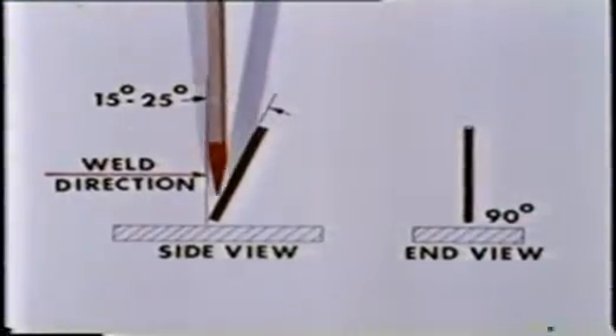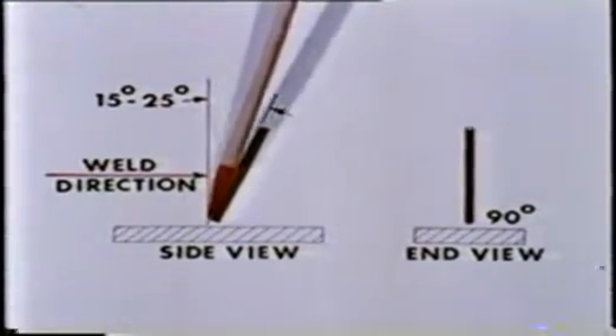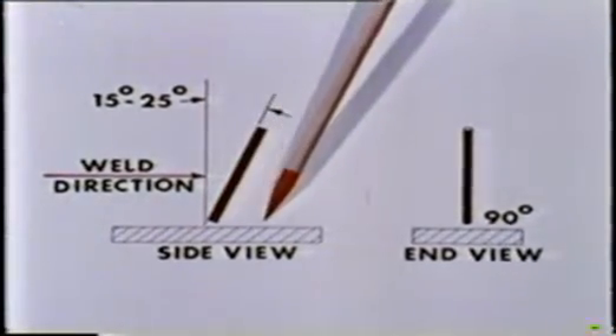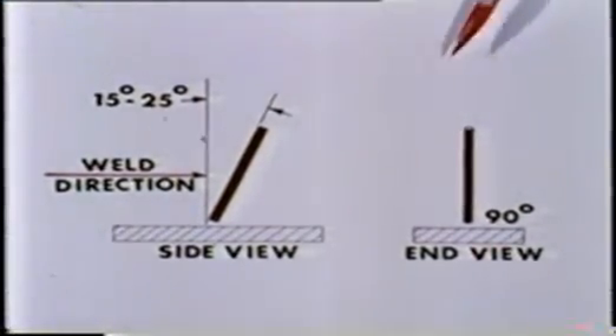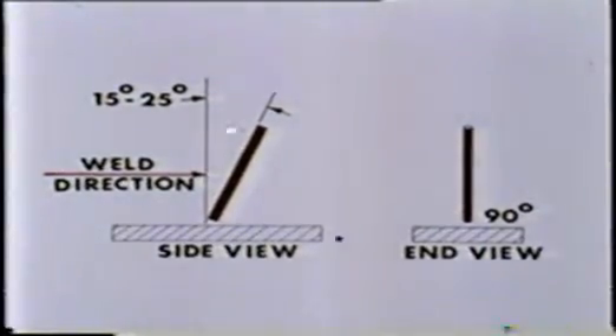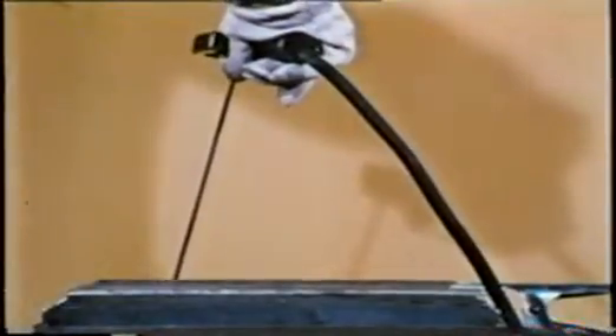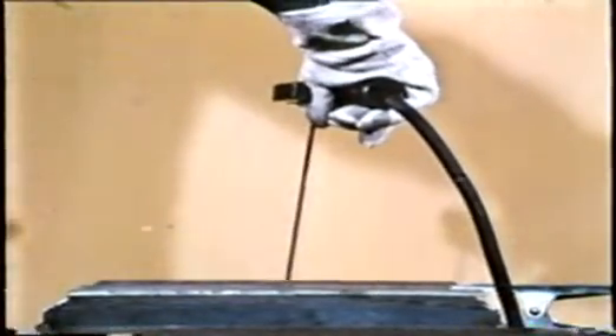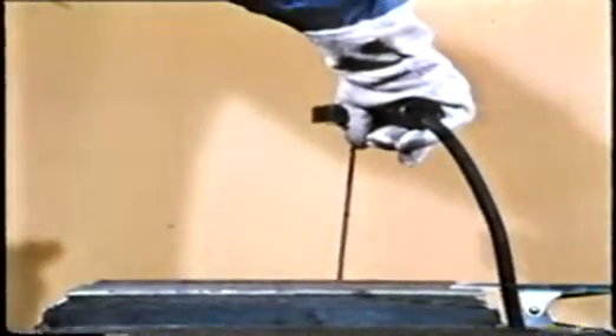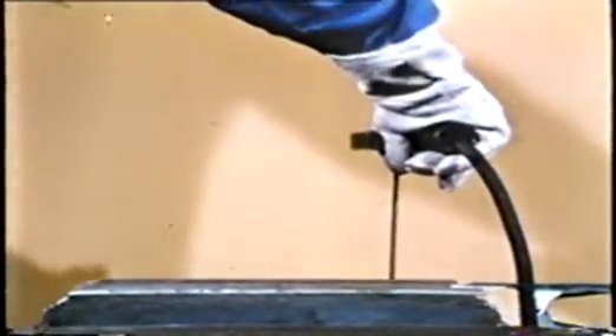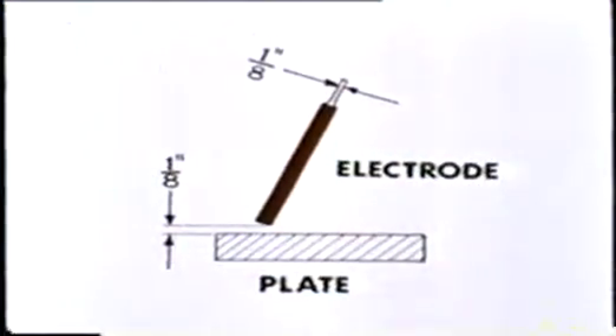After striking the arc, lean the electrode into the direction of travel, approximately 15 to 25 degrees. Notice the vertical electrode position is seen from the end view. Although exaggerated, this view does show that down-feeding of the electrode is necessary during welding travel, as it is consumed when it joins with the base metal.